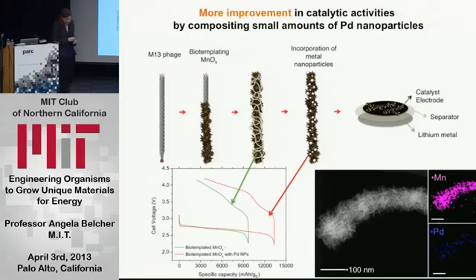And she showed, I didn't show the cycling data on this, but she showed the cycling data got greatly increased, because what we found out is that by making this three-dimensional network of these manganese oxide palladium materials, we could decrease the carbon content. And so we could make low carbon content electrodes. There were 8% carbon content electrodes, and the carbon decreases the cyclability of the system, because it has deleterious effects with the electrolyte, and she could greatly increase the cycling ability with this low carbon, mostly virus, manganese oxide based material that goes well over 70 cycles, which has been a big problem for lithium air, lithium oxygen batteries.